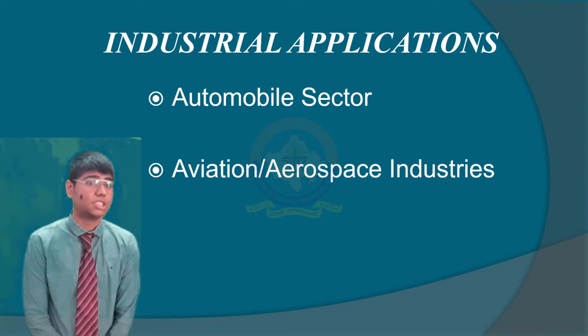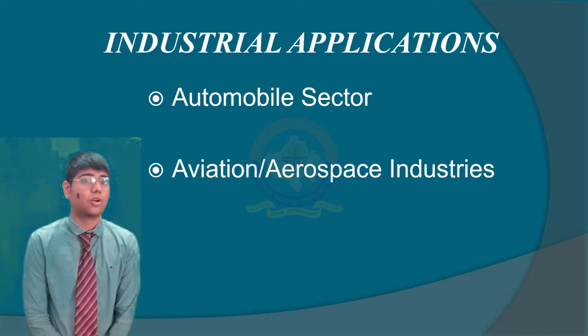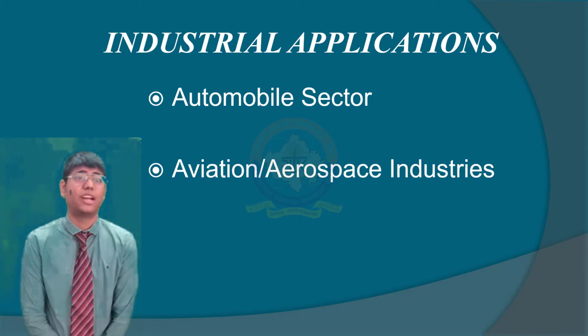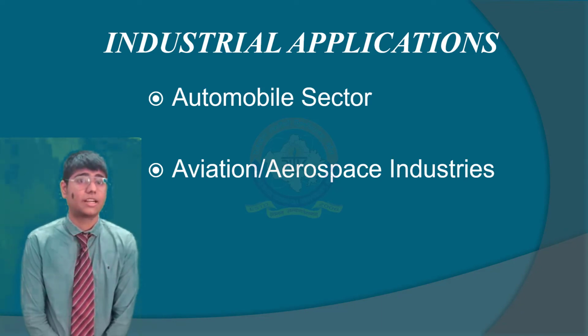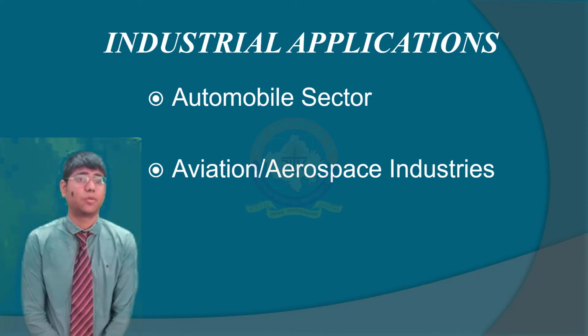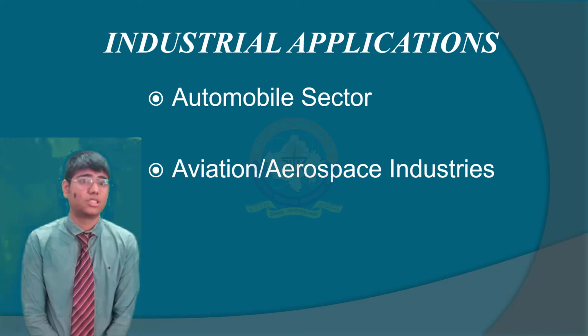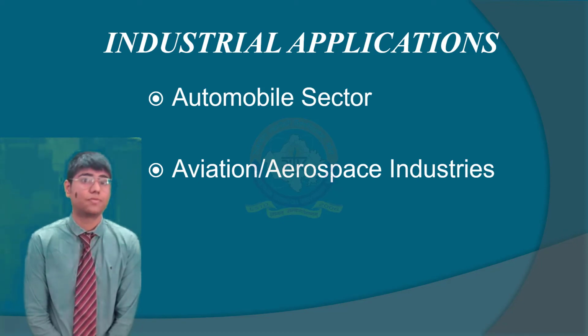Tube hydroforming examples of this include cradles, pillars and undercarriage. Undercarriages for vehicles were previously made of U-shaped or channel sections carefully shaped and then welded or riveted together. The U-shaped sections were produced by rolling, bending sheet metal or directly rolling a U-shaped channel, and cutting and welding it to others. Furthermore, because the weld is a compromise in the design, it will induce a change in material properties, and it's often a source of increased manufacturing cost and potential defects. This means welds require thicker sections and wider segments, which add cost and weight. Tube hydroforming removes this problem as it allows tubes to be welded while in tubular shape, then expanded to the final geometry, while becoming more rigid through strain hardening.